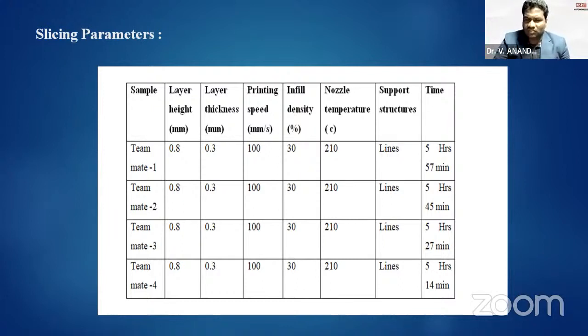And with this, after setting these process parameters, layer height 0.8 mm, layer thickness 0.3 mm, wall thickness, printing speed 100, infill density 30, nozzle temperature 210, bed temperature 60, support structures as lines, and infill pattern as grid, they sliced the component. After slicing, they came to know that the printing time of those models is around 5 to 6 hours.